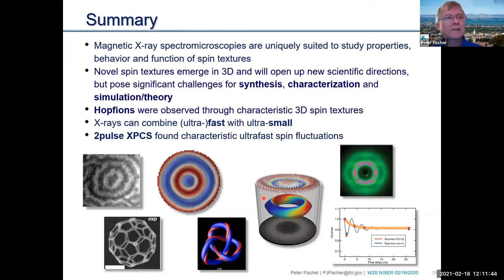Now, there is, of course, particularly on the scanning X-ray side, ways that people can put them on solid substrates. The reason is that you can detect different modes, like you can probe the local generation of currents, right? So when the X-rays hit a special location, there's a current, and you just record the current as you raster the scan across the sample. So if you really would like to do X-ray microscopy in real space with a sample that is not transparent for the X-rays, then I would recommend considering a STXM, just because it's probably a little easier. Keep in mind that a STXM is a scanning microscope. Scanning means it takes much longer. Scanning means you take point by point by point, right?